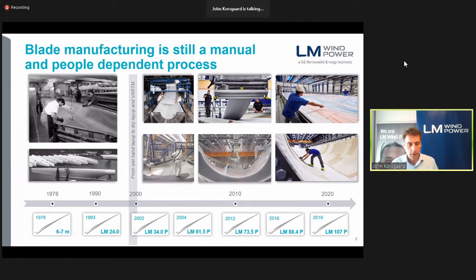The shift to the VARTM process happened in the late 90s, when the blade length had reached approximately 30 meters and a weight of 5 tons. The picture you see in the middle, just after year 2000, is how the dry layup was performed in the early days. As you can see, the layup is highly manual with no automation at all, and it was still fairly possible to position the reinforcement in the mold without having to walk on the dry laminate in the mold. And many of the process steps like gel coating, post molding, and finish were not changed at all.